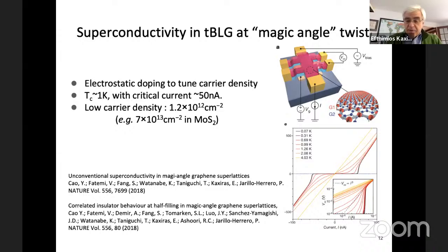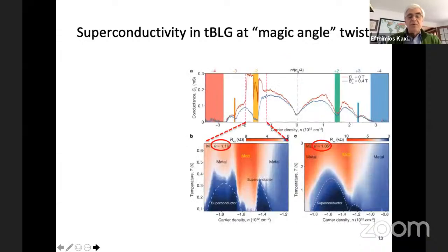Having carbon, basically graphene, behave as a superconductor was a big surprise because nobody expected carbon to be a superconductor. Typically metals are superconductors or some very special compounds, the copper oxides that become superconducting when doped to have also some type of metallic property. Graphene is a metal, but a very poor one, and it was not expected to have this behavior, but in twisted bilayer graphene, it does indeed become superconducting.